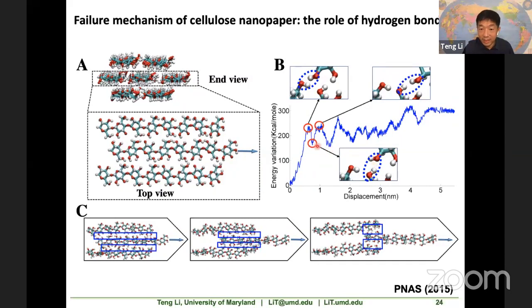So when you further slide, this energy picks up. So this happens many times during the sliding process. So this clearly captured this deformation and the failure mechanism we envision, which is the hydrogen bond forming, breaking, and reforming, and in terms of the zigzag nature of the energy variation.